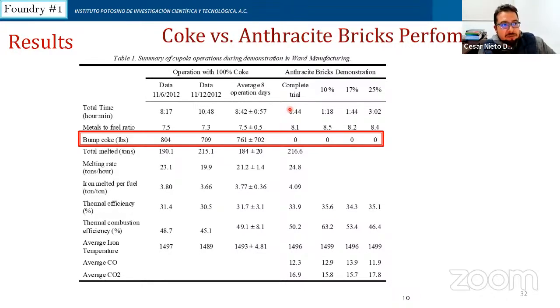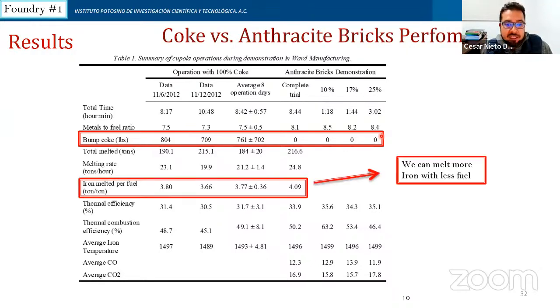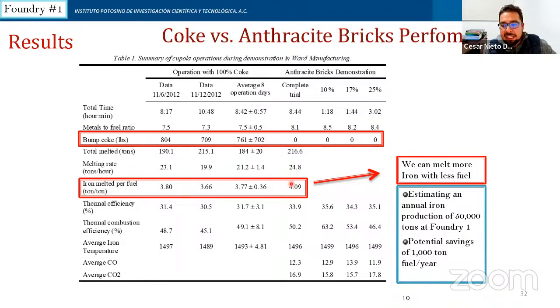Something that Foundry number one usually does is make a bump of coke. They just make one load full of coke because sometimes the temperature goes low. In these 3 columns is the amount of extra coke that they use when they were using coke, and in these columns is the extra coke that they needed when they were using anthracite briquettes. And you can see they didn't use any extra coke. Also, the iron melted per fuel was very high when we were using anthracite bricks, which means that we can melt more iron with less fuel. And just to put numbers on it, for the production of this Foundry number one, the potential savings is around 1,000 tons of fuel per year.